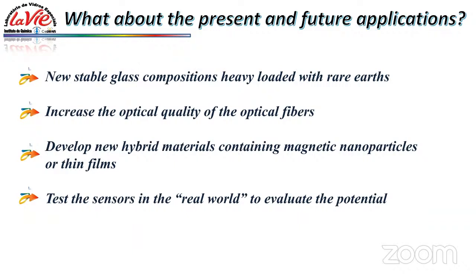And just closing this presentation, we need to work with new stable glass compositions with a lot of erbium, for example, inside to increase the Verdet constant, and increase the optical quality of the optical fibers we obtained, because we never did something in this direction. Now we are working on the purification of these fibers and on removing the water, for example. Develop new hybrid materials containing magnetic nanoparticles that can be used as glass or thin films, and test the sensors, of course, in the real world to evaluate the potential of these materials.